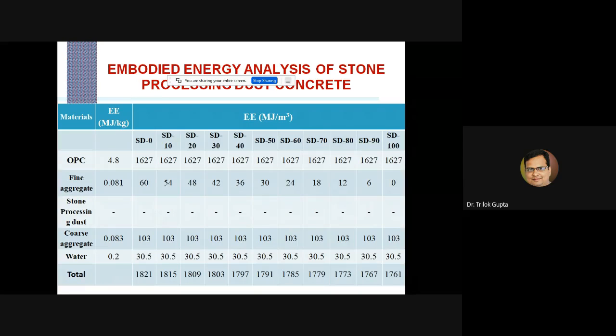In that research, it was given that 4.8 megajoules of energy is required to produce 1 kg of cement, whereas for fine aggregate and coarse aggregate it is very little. In the case of water, we require some filtration and pumping from the filtration plant to an elevated service reservoir, and from there gravitational force is used. So that's why it is very, very little. Ultimately, from this figure, the embodied energy required for 30% replacement is less than for 0% replacement, and at 100% replacement it is the lowest value compared to the control mix.